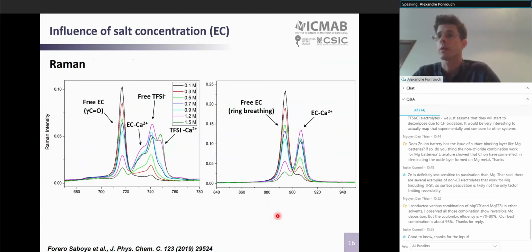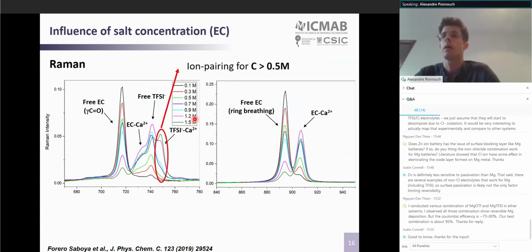So once again, with Raman spectroscopy, you can see for the example given here for the calcium TFSI in ethylene carbonate based electrolyte, for a solution ranging from 0.1 molar up to 1.5 molar, we can identify two major issues potentially for these electrolytes. The first one is that we start to observe contact ion pairs at salt concentration as low as 0.5 molar. So we have to be careful about the formation of these contact ion pairs for very low concentration, in fact.